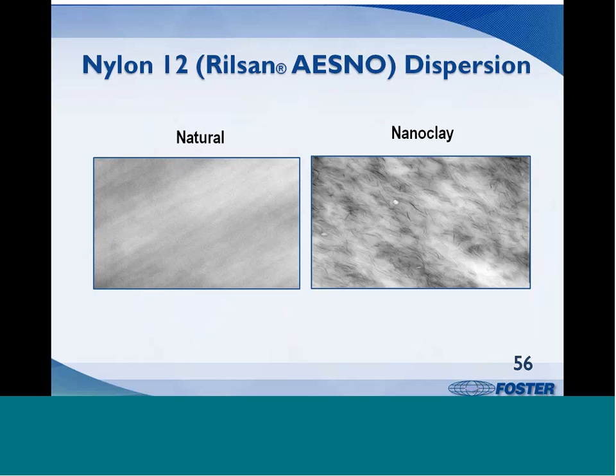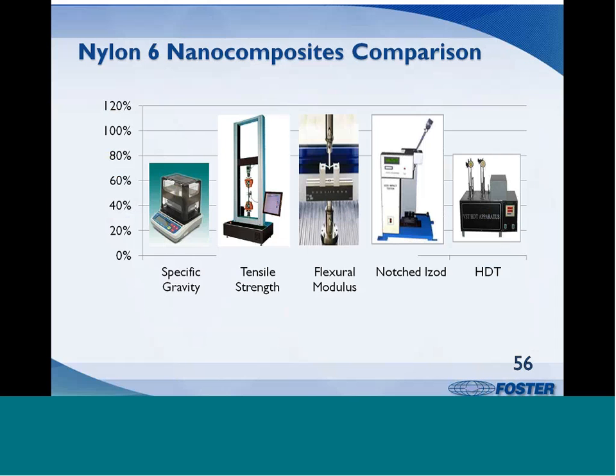These photomicrographs show the fine dispersion of nanoclay that can be achieved in a composite. The difference in properties between the reactor and compounding routes was characterized by specific gravity, tensile strength, flexural modulus, notched izod pendulum impact, and heat distortion temperature testing.